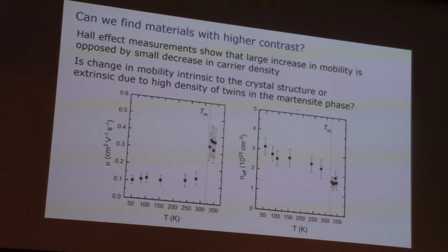We measured the electronic mobility and the effective carrier densities using Hall effect measurements. This is not so easy because the materials are magnetic, and so there's anomalous Hall effects involved. But I have some people that know more about this than I do, and they were able to extract that the mobility increases almost a factor of 3 at the transition, while the effective carrier density drops a little bit, and that kind of explains the properties of the material.